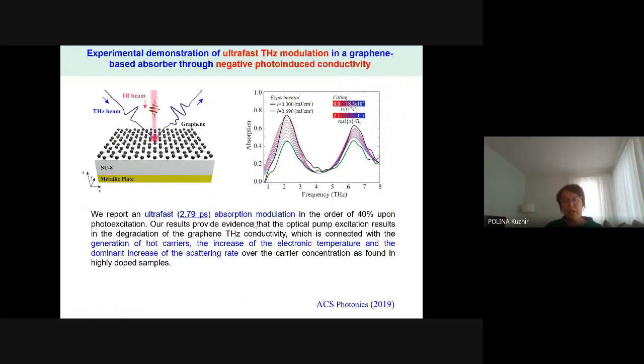Another interesting way to tune the electromagnetic absorption of graphene is to illuminate the graphene layer with an infrared beam. This generates hot carriers, increasing the electronic temperature, which substantially increases the scattering rate, suppressing the conductivity and thereby the absorption ability. What's really nice is that these processes are ultra fast. To modulate the amplitude of the electromagnetic wave, changing absorption from 80% to 40%, you need less than 3 picoseconds of infrared radiation.